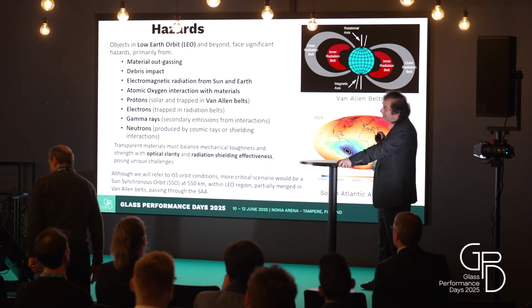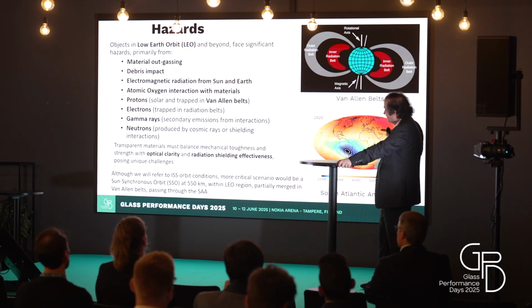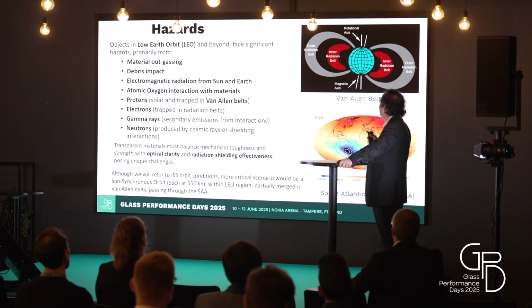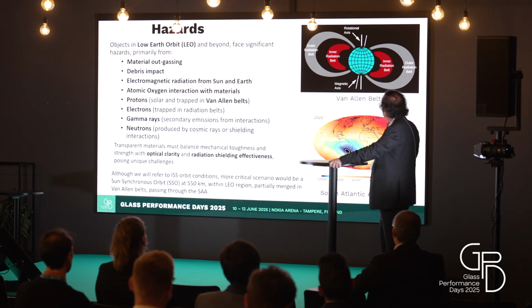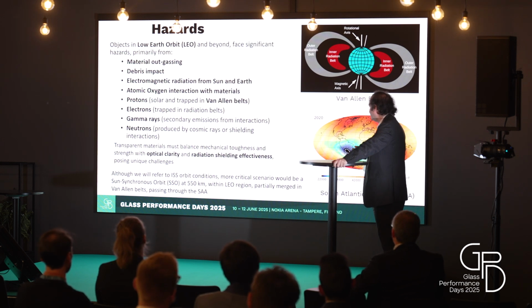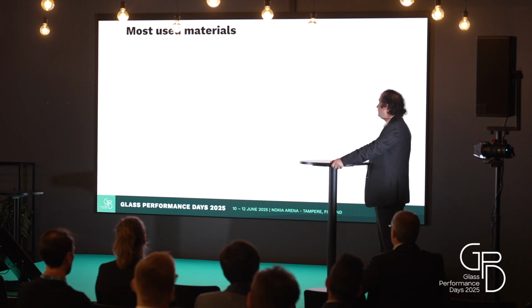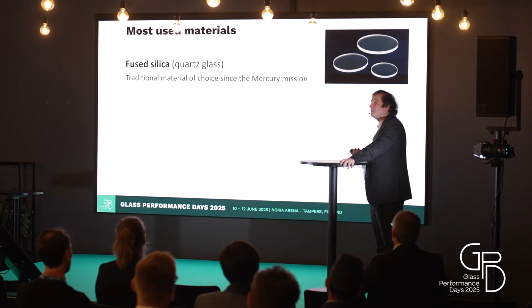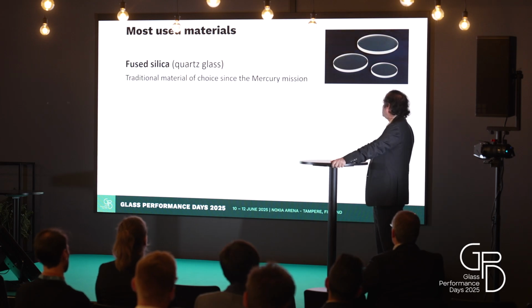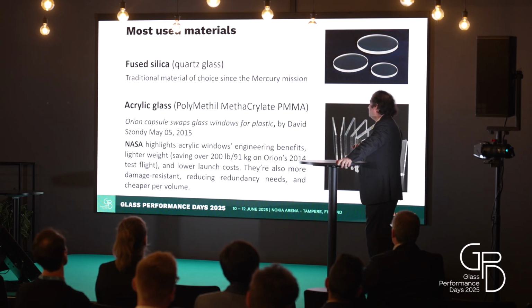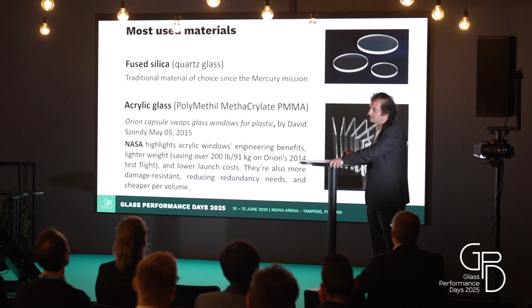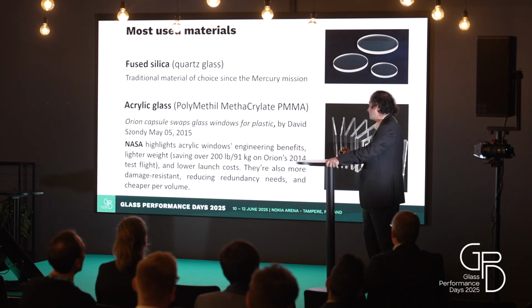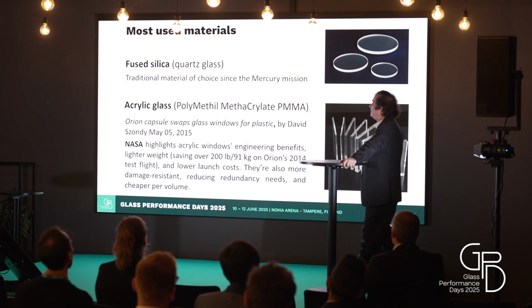within the low Earth orbit region, which is partially merged in the Van Allen belts and also passes through the South Atlantic anomaly, where there is an environment at a lower altitude which is very similar to that caused by the Van Allen belts. Which are the most used materials? Fused silica is the one that has been traditionally used, but in recent years also acrylic glass is being used for pressure windows, and we are presently working very much with acrylic glass.